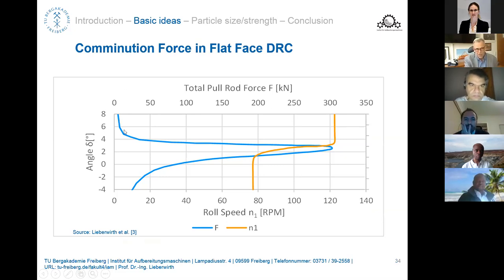This is again a graph drawn from our flat face double roll crusher here, which we've seen in the movie, which is equipped with a force measuring device over the roll angle. And what we could see there was a pretty similar picture to what you would find with the HPGRs. Here we have the angle 0, which is the connection line between the two roll centers, and just about 2 or 2.5 degrees on top of it, you have the maximum force acting on the rollers when crushing a lump there. So which is a curve which is very well known from HPGRs, very similar. And we found it confirmed even with a double roll crusher.